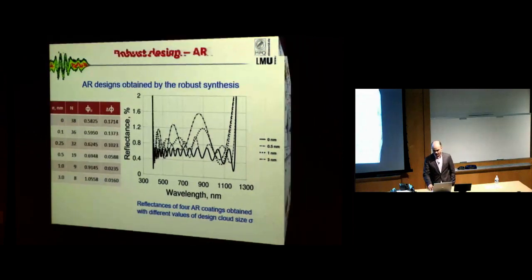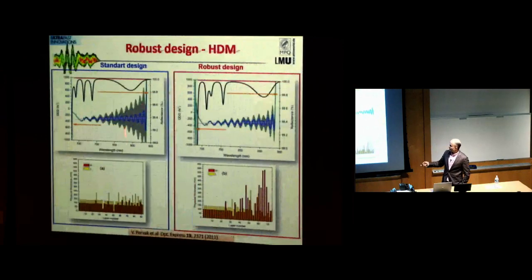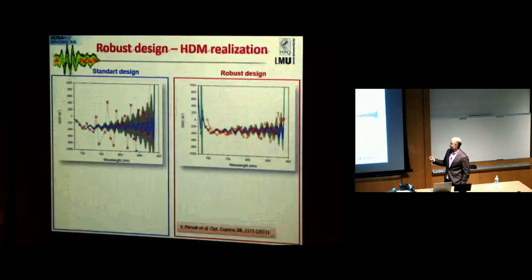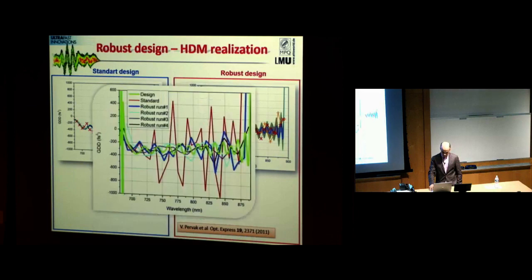And when we apply this to chirped mirrors, this is a conventional design, and this is the robust design. The layer structure looks completely different, two completely different structures. They do approximately the same job, but they look very different. And here is a comparison of the final result. This is the measurement of the original mirrors, and this is the robust design. The crosses are much closer to the theoretical curve.